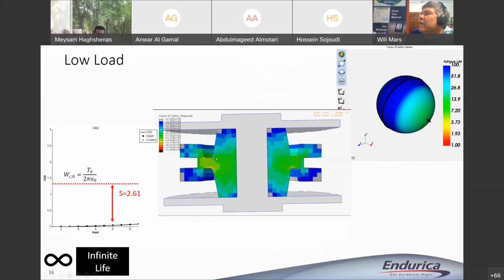So this is an overlay. I've animated the part so you can see this is the load. This is the low load case. You can see there's sort of a rocking motion of the grommet. And I've colored the model according to the safety factor that's been computed with critical plane analysis. If you see red, that's a safety factor of 1.0. If you see black, that is where the safety factor is below 1, right? So that's not infinite life. Everywhere else is infinite life, and blue is a very large safety factor. Red is just on the line.